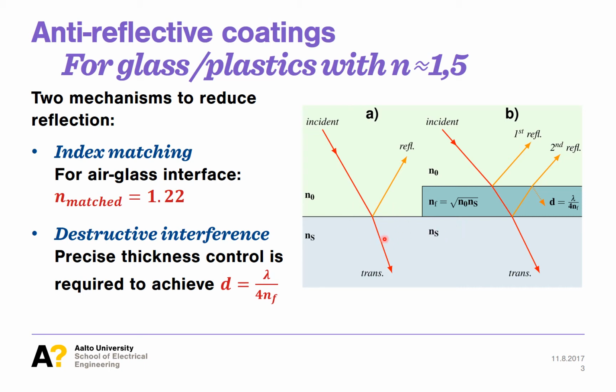Fresnel reflection is minimized when the refractive index of the introduced film, NF, is the geometric mean of the two original indices, N0 and NS in the picture. Most glasses and plastics have a refractive index of about 1.5. For an interface of such a material with air, the index matching coating should have a refractive index of approximately 1.22.